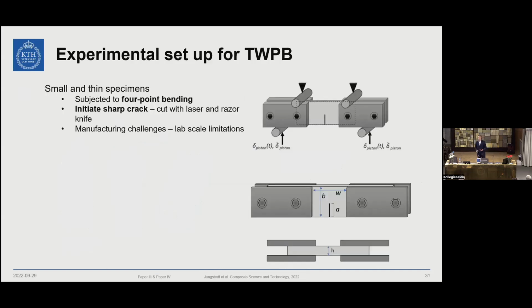So how we will investigate this material is by doing 4-point bending. We will initiate a sharp crack with a laser and a razor knife. And the reason why we use small, thin specimens is because this material is not made on an industrial scale. We're making it ourselves. It's quite new.